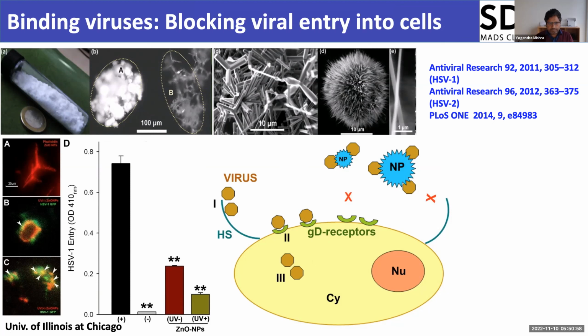That's what we learned. And we found out that the tetrapods capture more viruses if we illuminate them with UV light. UV light means it has a band gap of 3.37 electron volts, so you create electron-hole pairs. The electron goes to the conduction band, and then oxygen is happy to take it and go off. So this creates more oxygen vacancies, which are positively charged, and they help in more binding.